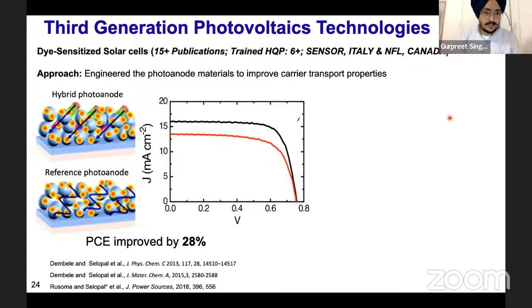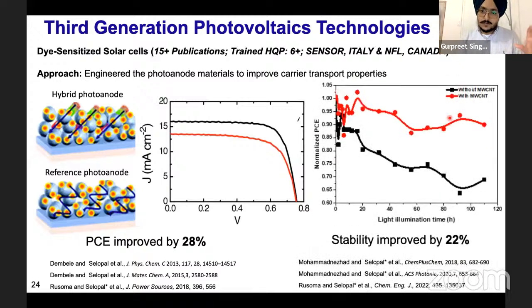low dimensional carbon materials. And I'm very proud to announce that during my PhD we were the first scientists to demonstrate the mechanism behind this enhancement in the power conversion efficiency by using a very small amount of carbon material. I have continued working in this direction with the help of my team, and we also improved the long-term stability by 22%. Because of these achievements, we were contacted by two Canadian companies to use this technology in their organic solar cells.